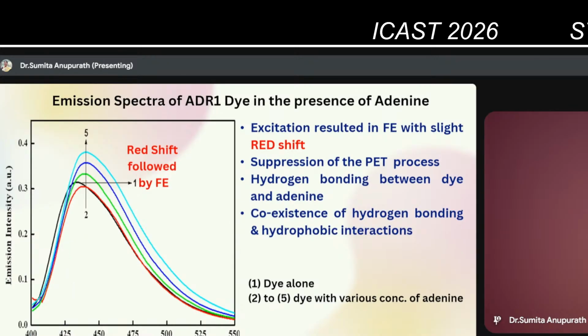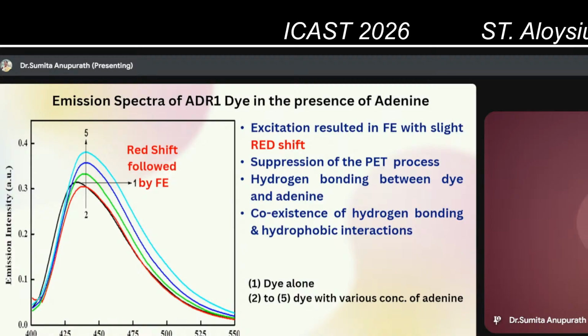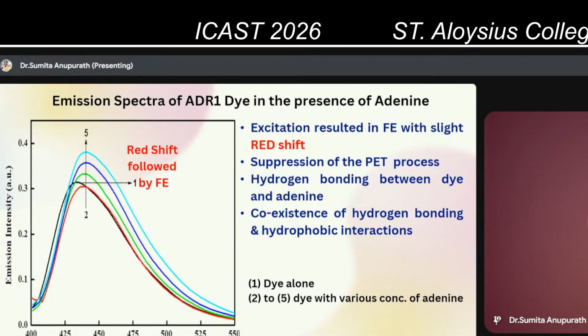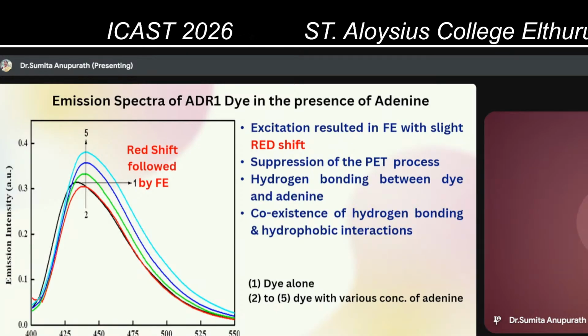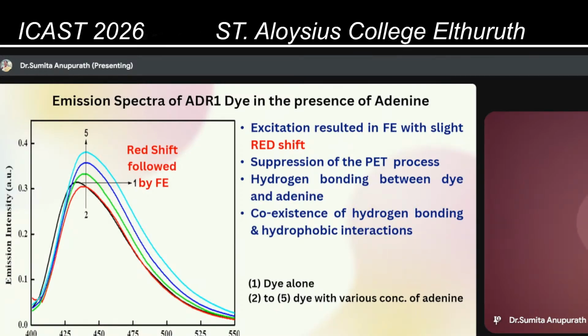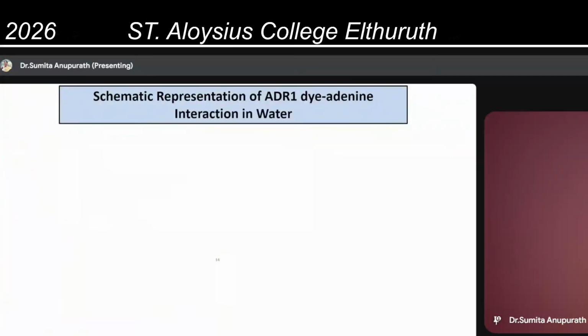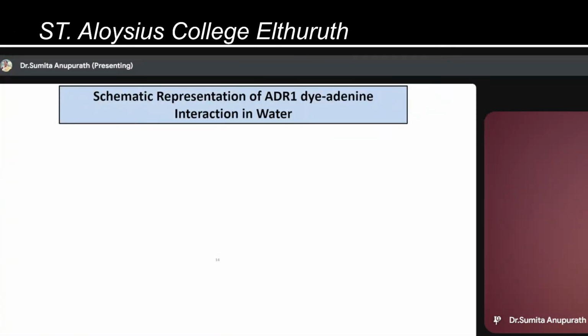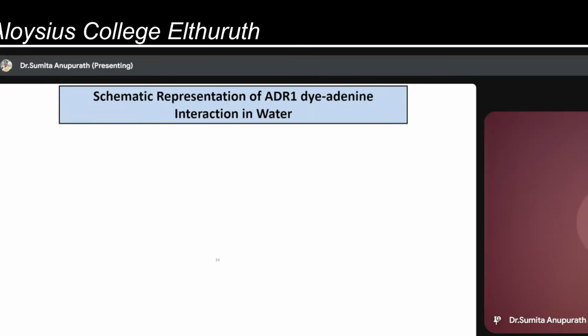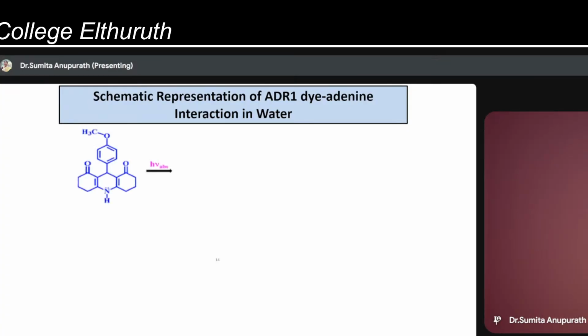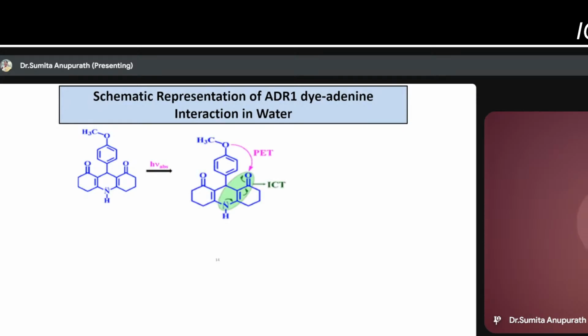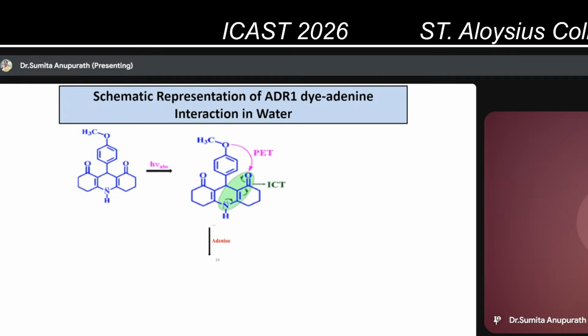Now, this fluorescent enhancement and the slight red shift observed can be attributed to the hydrogen bonding interaction, which we can further validate with other studies. So to understand the interaction in a better way, this is a schematic representation of ADR1, that is the PET dye, with adenine. The dye absorbs the light, and the ICT process and the PET process take place. Now to this system, when we add adenine, it has various possibilities to combine with the dye.